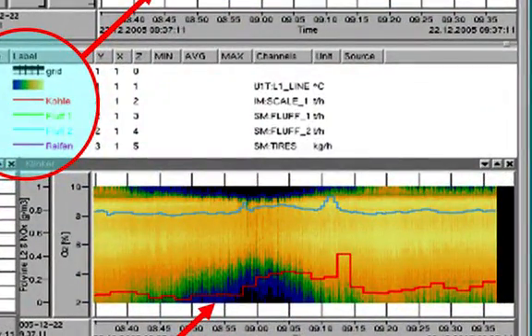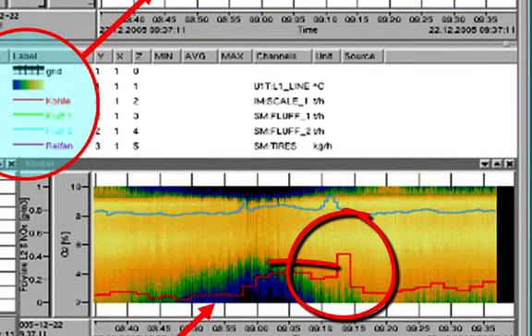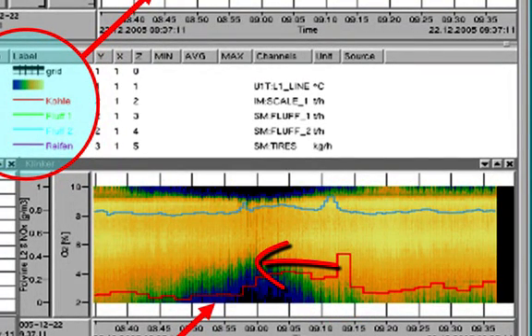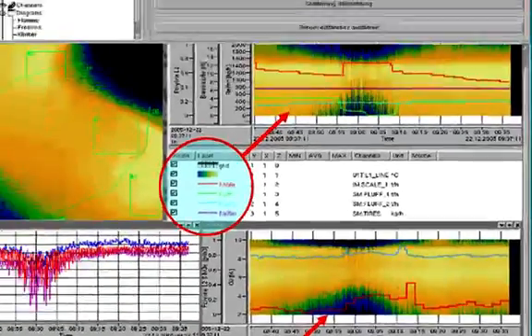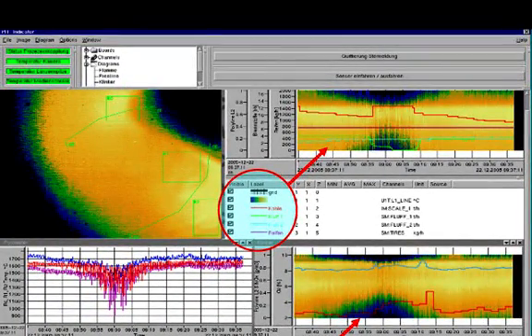The lower diagram shows the NOx measurements and O2 at the chimney without time correction. The NOx peak is measured about 15 minutes after it was produced at the flame. This clearly shows that the polylines together with the process values can be used to optimize the process and to react earlier.